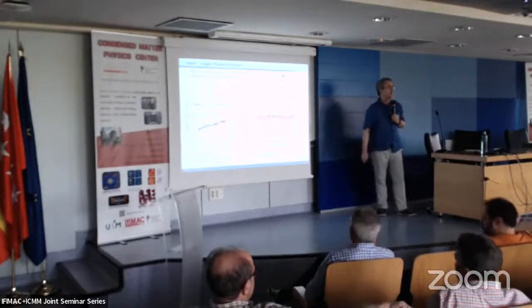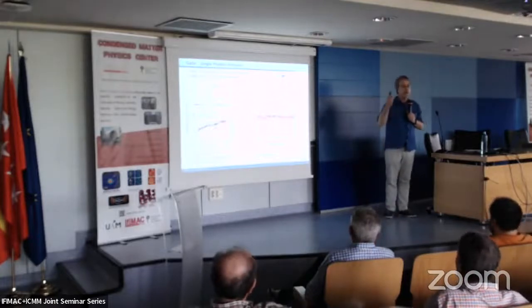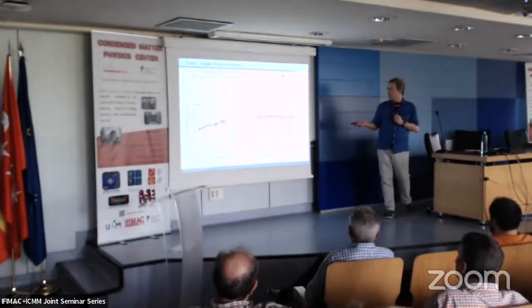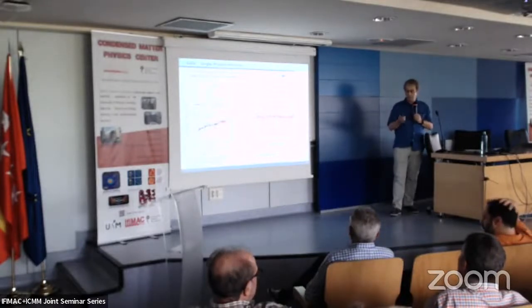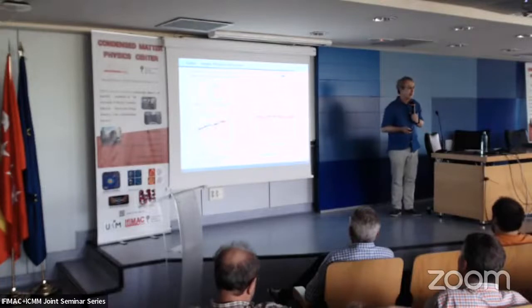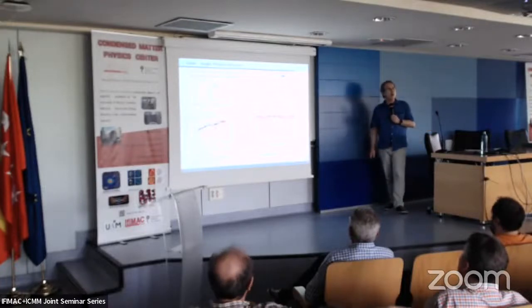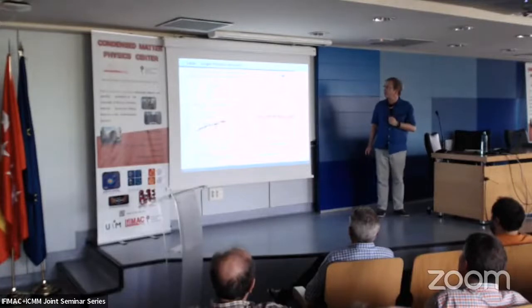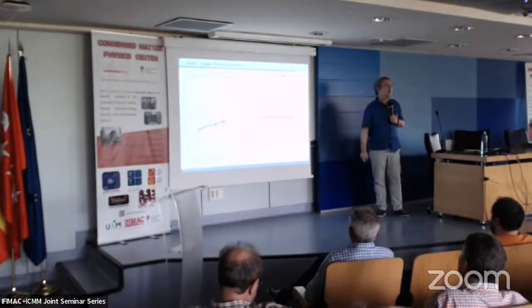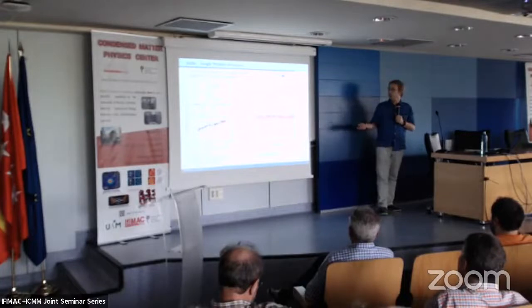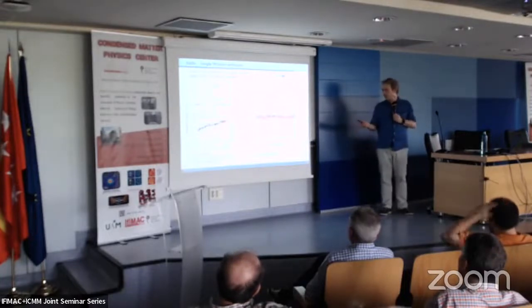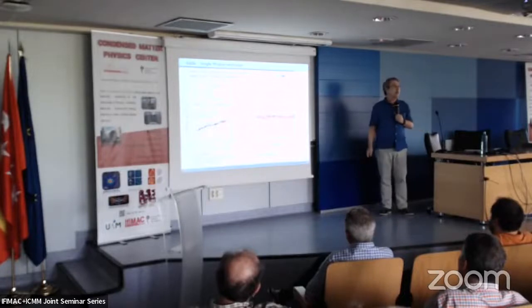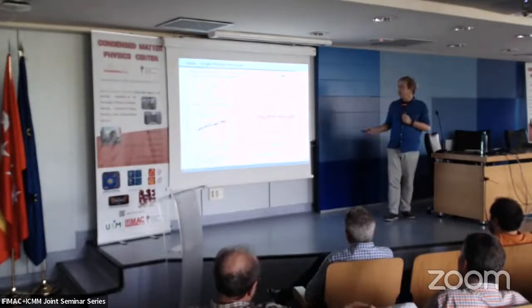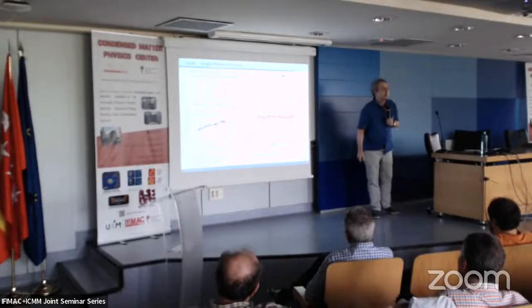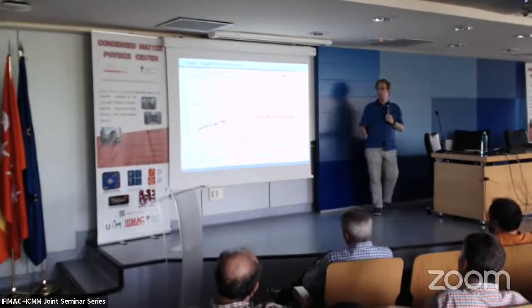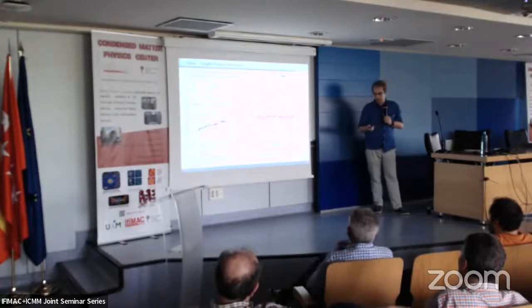Our problem with this sample is that after a very long search in different dots, these materials show degradation on cycling the temperature a lot of times. So this one died, the sample. And this is the point where we were just before the pandemic started. And so now we want to pick up where we stopped at that moment and look for new candidates for this single photon emission, and eventually see if this was just one shot or it's really some effect which we can explain.